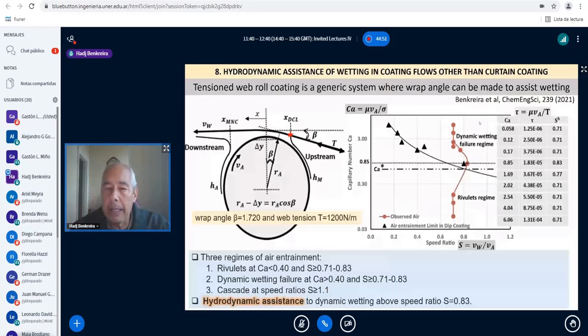Now let's look at the hydrodynamic effect. Even with the normal coating situation, and this is some recent work that we've just published, we looked at the situation where you have a web which is wrapped around the roller, and you're bringing a film, and in here you're looking at the air entrainment in that situation. And even in that situation, we observe that by playing with the hydrodynamic in here, simply by changing the wrap angle, you can affect the air entrainment velocity significantly as against, for example, dip coating.